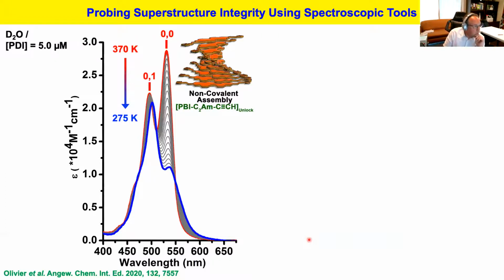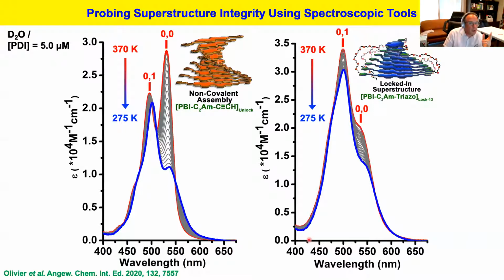So now what can we do with them, right? Again, I showed you that before many times, so I won't go into too much detail, but the parent non-covalent assembly: high temperature, molecularly dissolved; low temperature, aggregated. Nothing really new here. But what's very interesting is that now that we have this additional covalent tether essentially decorating the periphery of the stacks, at a temperature at which the non-covalent assembly is fully dissociated, you can see that the spectroscopic signature in red here at high temperature is reminiscent of that of an aggregate. So what that tells us is that essentially even at high temperature, these PDI units are still electronically coupled, okay? So that's a good indication that this covalent tethering is working.